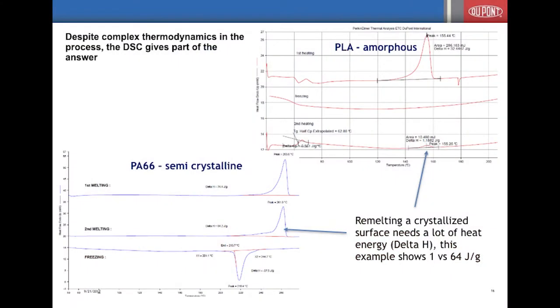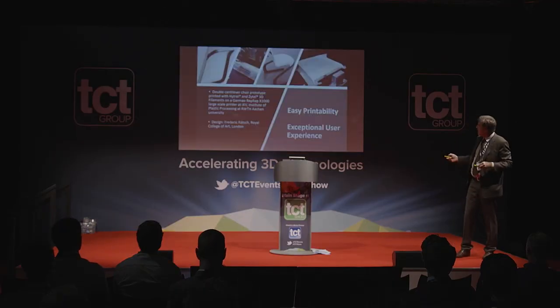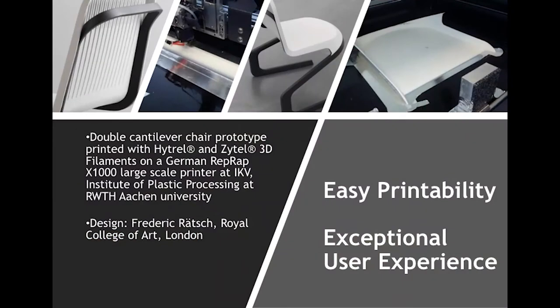When you take polyamide 66, it melts at 261°C — a huge peak — but when it freezes it releases energy at a much lower temperature, around 220°C. So a frozen surface skin of PA66 can only be remelted when you get this energy in at the right temperature, but the next layer absorbs it at a lower temperature level — a couple of dilemmas that are not very helpful. These are things the industry and chemical companies have to think about to improve polymer capabilities for additive manufacturing.